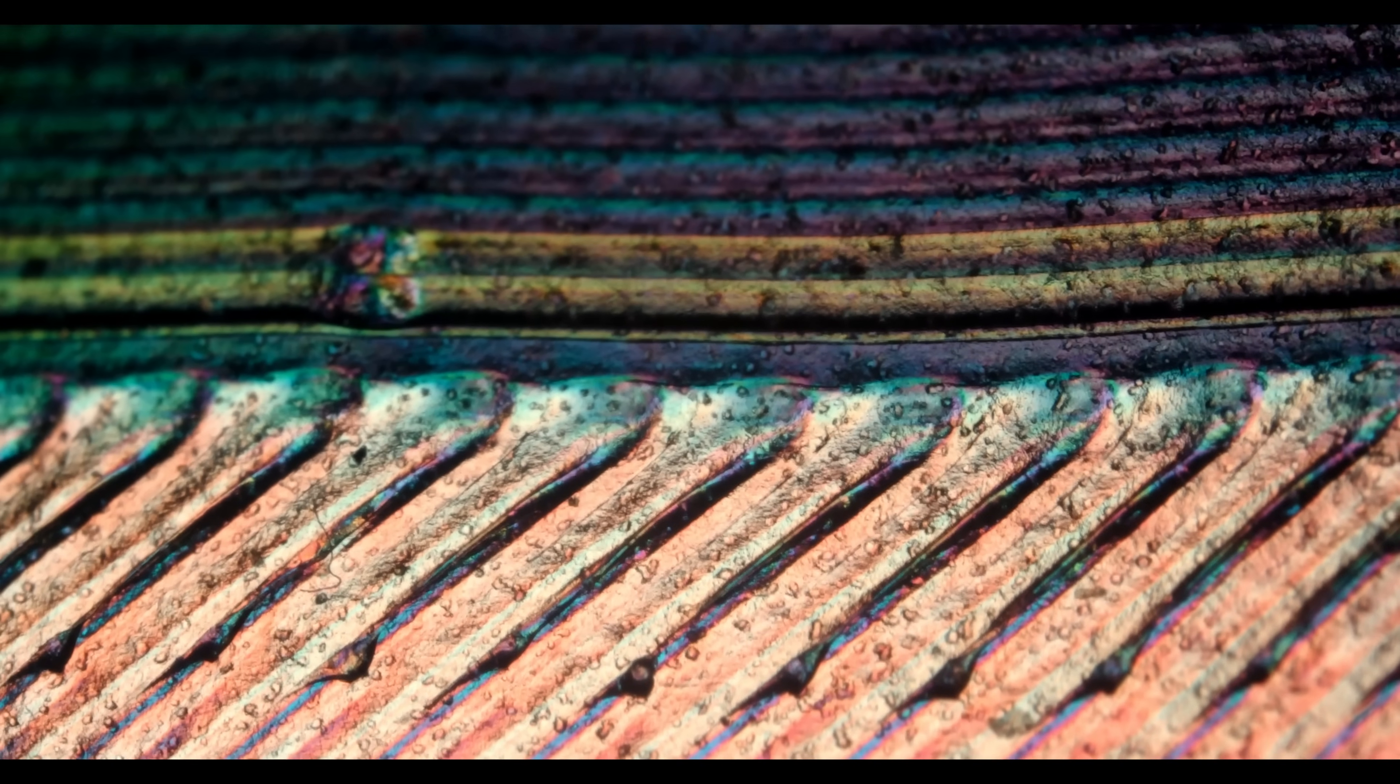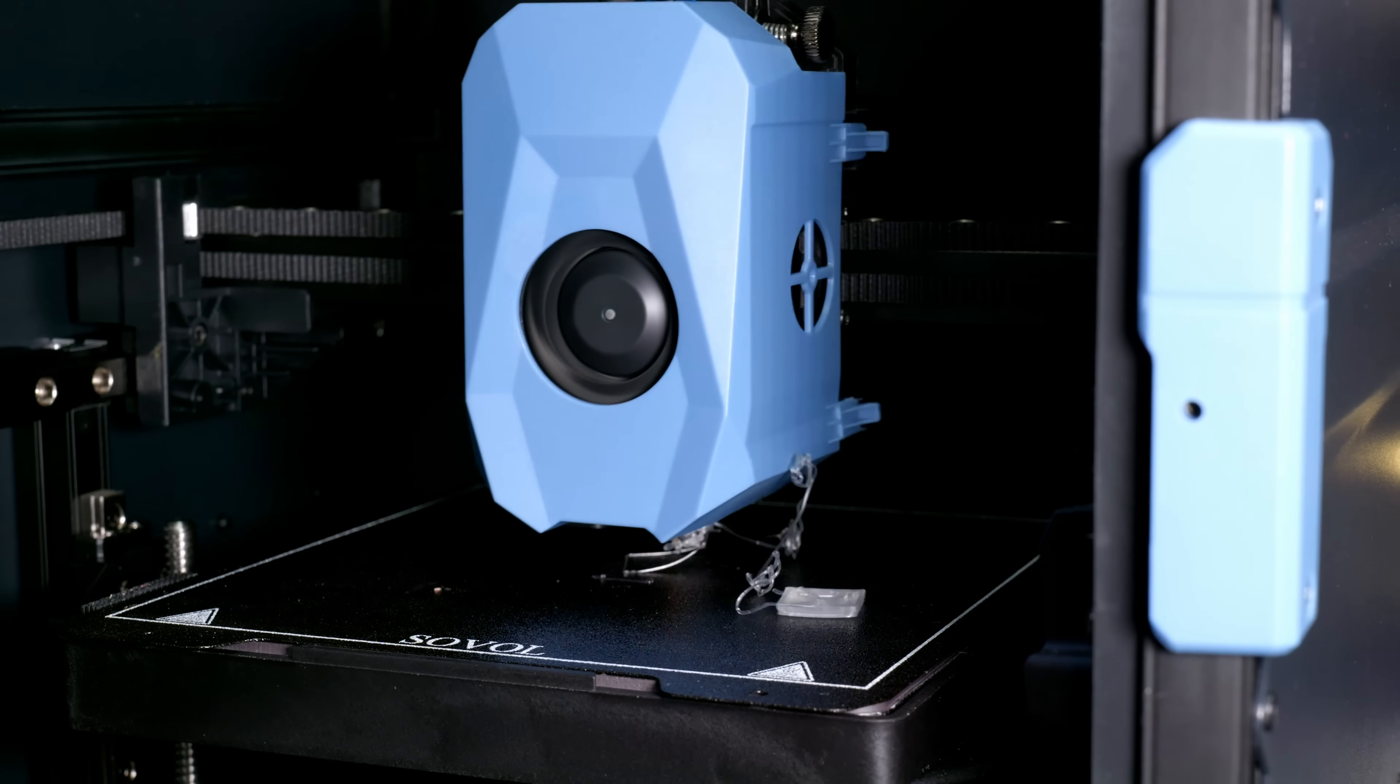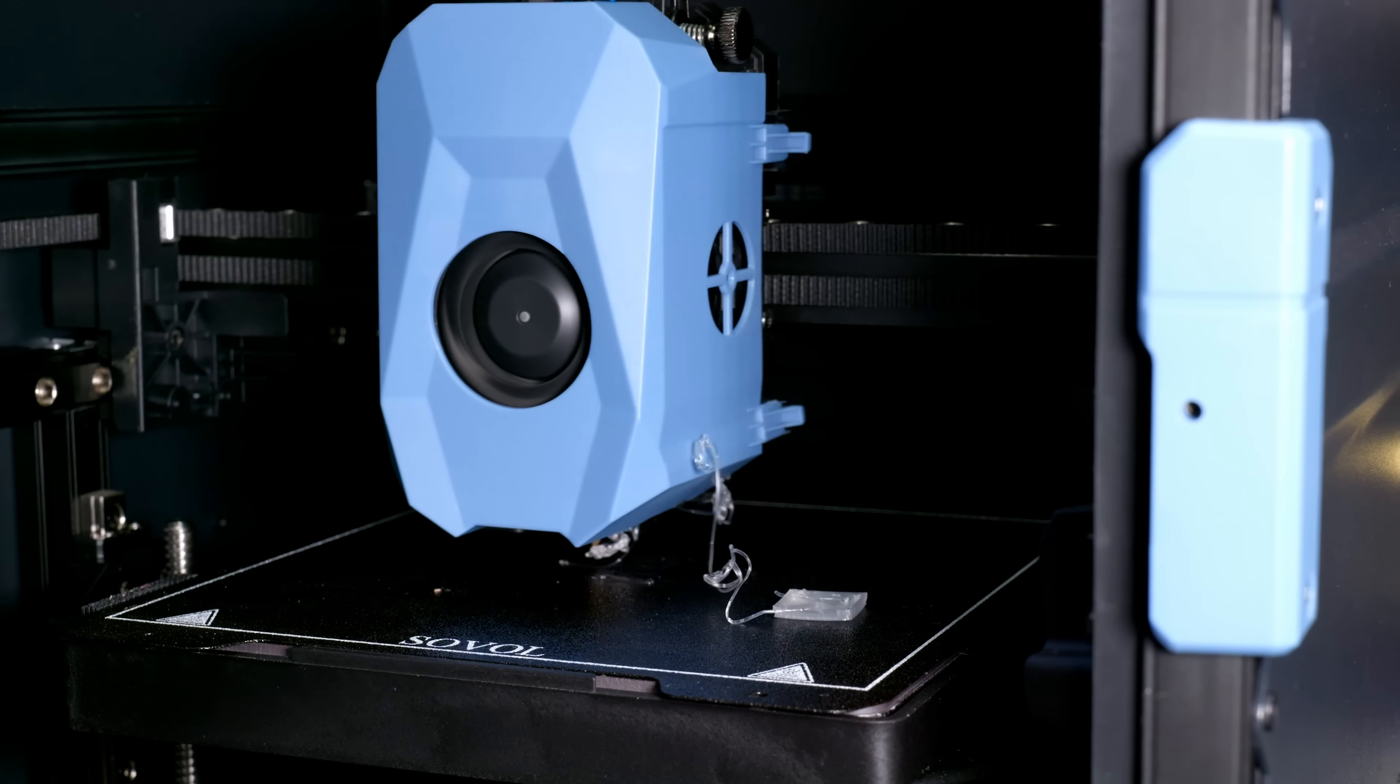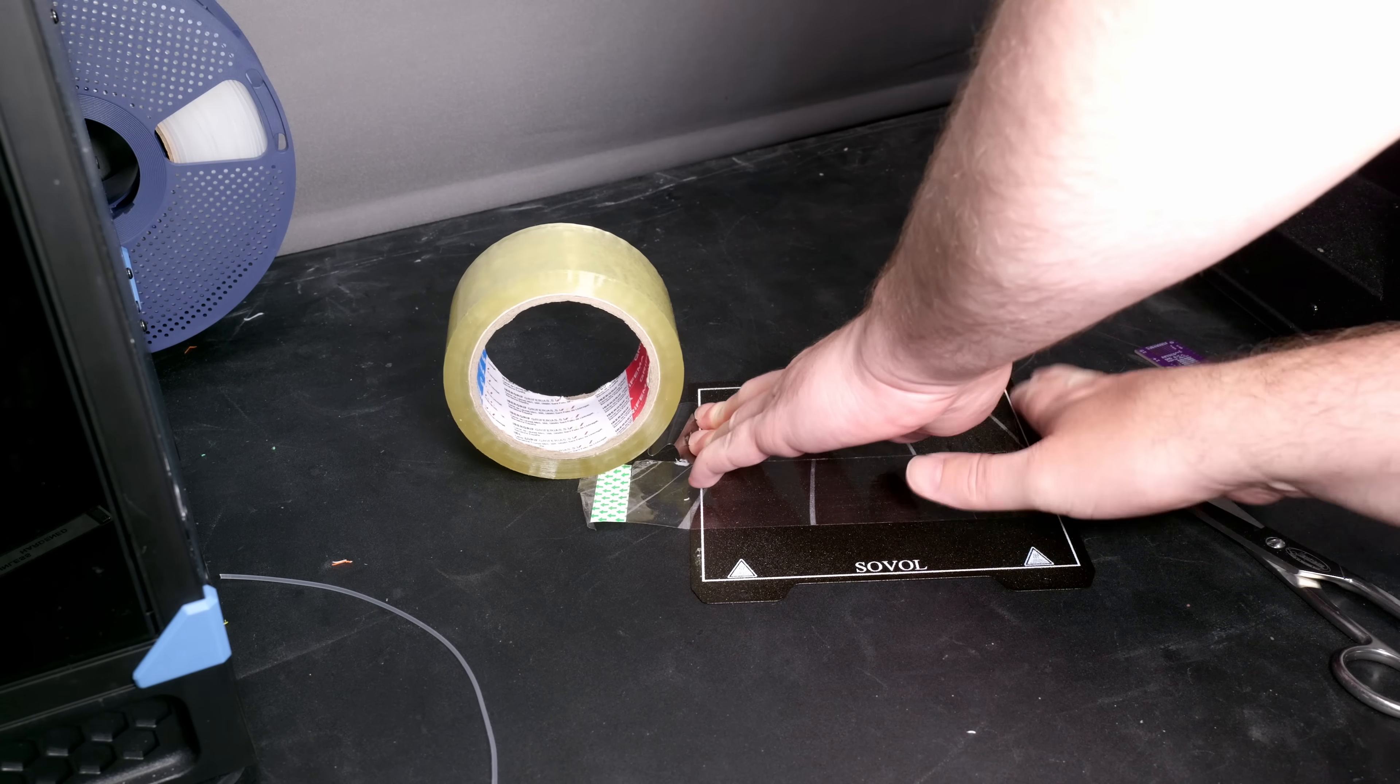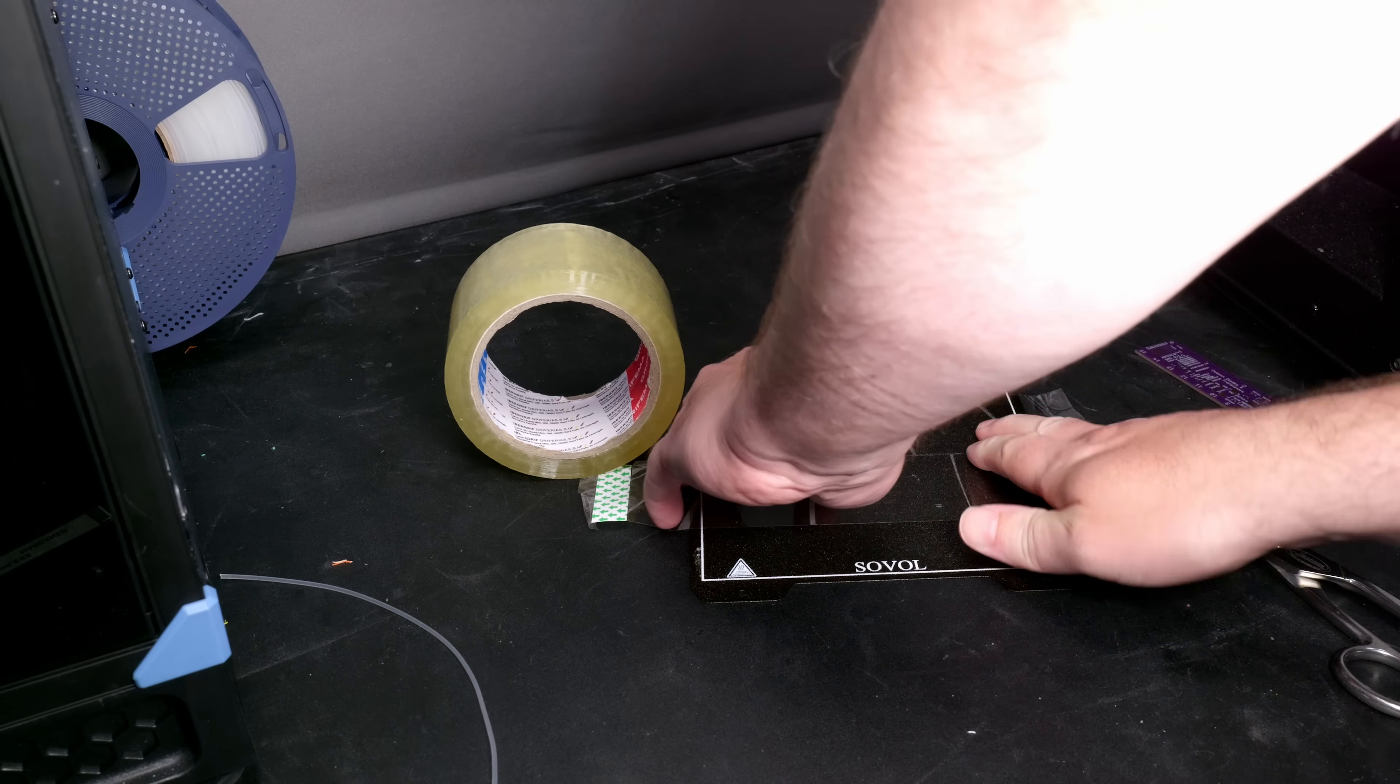This is caused by something called birefringence and it's actually complicated because not only crystalline stuff does this the plastic can do this under stress even if it's not crystalline so yeah there's at least two reasons in this case with polypropylene that it's showing these colours, intrinsic semi crystalline structure of the polymer which is what made me look at it in the first place but it will also show the stresses that were cooled into the plastic. It's just something I found out about along the way and I thought I'll try that and what do you know it works and it's another excuse to show you something cool through a macro lens.